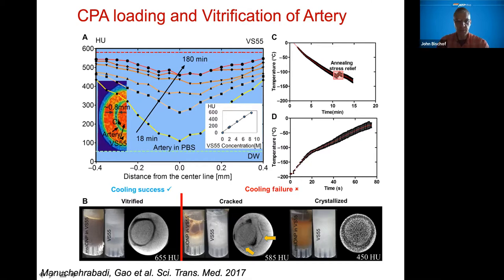And this on the top left is really micro CT advanced imaging to tell us when we had actually loaded sufficiently in the artery the different cryoprotectants. So this is VS55, it's a cocktail that we use. And this is showing in steps of 18 minutes, up to 180 minutes, how well we've actually permeated the cryoprotectant into the artery.